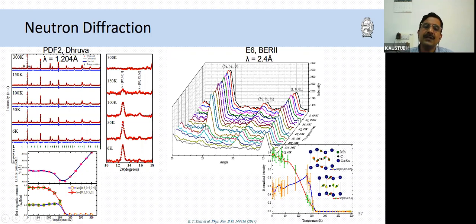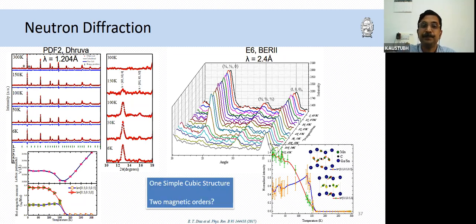And in both cases, we could clearly see two magnetic peaks, one from the half-half-zero wave vector, which is similar to that of Mn3SnC, and the other one coming from half-half-half, which is similar to that of Mn3GaC. So within a cubic structure, there are two magnetic orders that are being stabilized. One is similar to that in the one end member, the other is similar to that in the other end member. But the overall global structure is single phase cubic. The only thing is that the width of the peak was the highest as compared to the others.